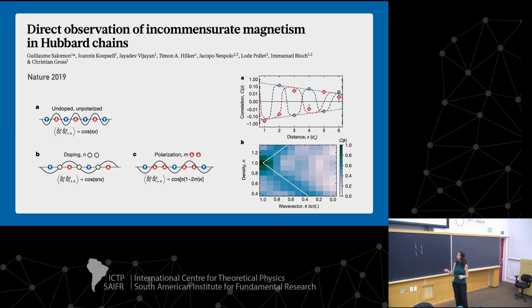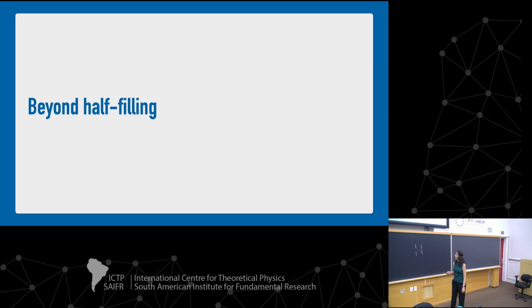So this perfect up-down order is obviously going to be distorted because you don't have atoms to have up and down in each one. And so you start to have a wavelength here that is repeated that can be different than, not commensurate to, your lattice. And this is a very beautiful experiment, once again from Immanuel Bloch's group, where he is looking at the wave vector of this wave here that is trying to match the periodic organization of the spins in the lattice, and you see that you have some that don't quite match the size of the lattice. So this is something that is very interesting, and people were trying to see it, and this is the first time that it was seen.